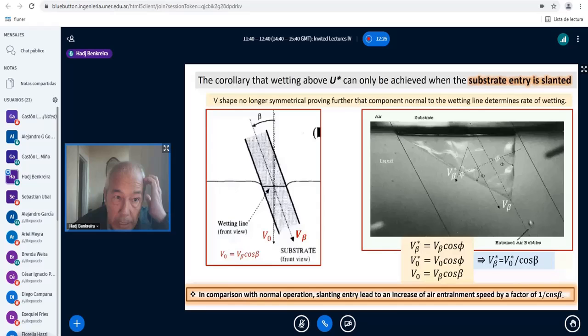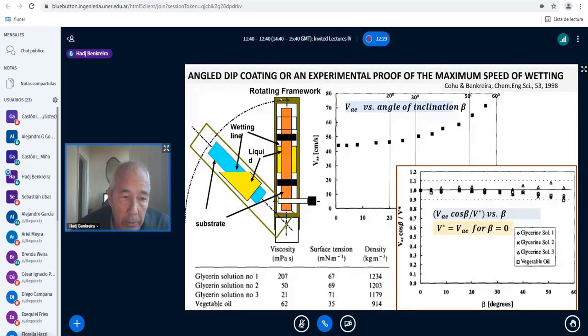And we went ahead and did the experiment. Here, as you see, this is the coating rig where we have the dip coater, and we simply tilt it at an angle and then drive the substrate in this way so that the substrate enters at an angle. And when we measured the air entrainment speed, we observed that it increased as you increase the angle, so much so that it actually doubled at 60 degrees, which corresponds to 1 over cos beta. 1 over cos 60 is equal to 2. So effectively, we could already double the production rate simply by changing the angle of entry into the wetting line.